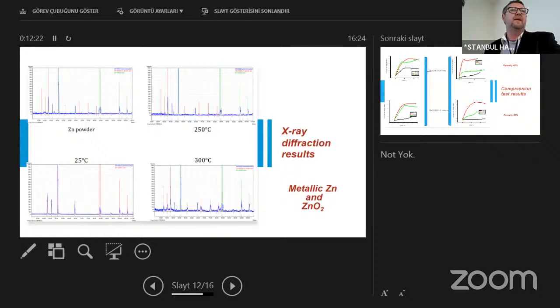If we heat it to higher temperatures, besides this decomposition, some oxidation also takes place because everything is done in air. So the zinc oxide content is higher—it can go up to 20%. The powder we started with had about 5% oxide. At 250 degrees there will be around 10–12%, and around 20% at the highest temperature.